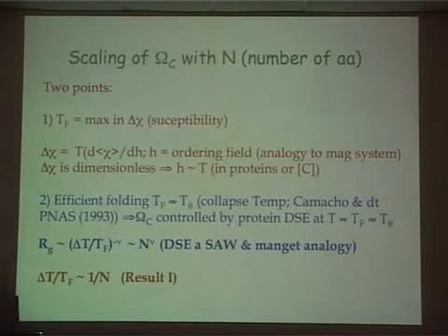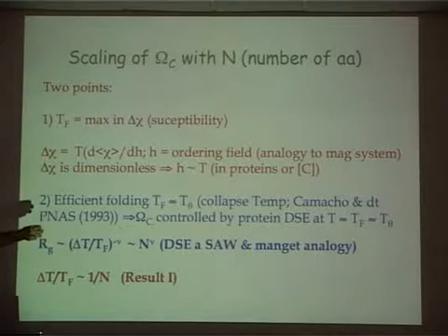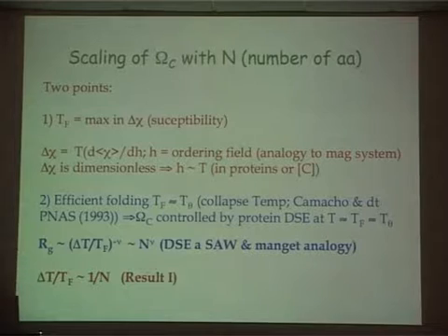And the way you identify the folding temperature is it's a maximum in the susceptibility, delta chi, which will be just chi squared average minus chi average squared. And chi is this overlap parameter, which tells you how similar a given conformation is to the folded conformation. This is really like susceptibility in magnetic systems. And you know the susceptibility in magnetic system can be written as a temperature times the average order parameter with respect to some ordering field, right? You can write this. These are two same things. It's linear response. The ordering field is the magnetic field in spin systems, say. And here delta chi is dimensionless, so I can say that the ordering field here must correspond to temperature itself, or in the presence of denaturants, it corresponds to the denaturant concentration.